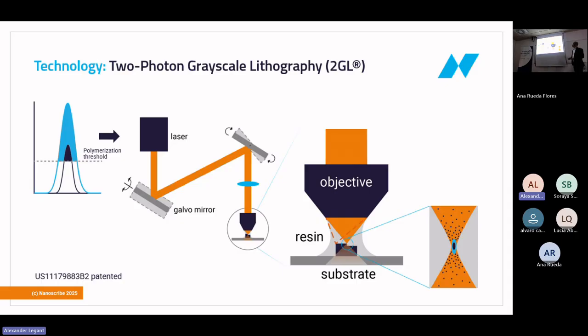Now the next step forward is that we also use two-photon grayscale lithography. We have a patent on that. If you look at what happens at the laser intensity level, at the voxel level, polymerization takes place only if the laser intensity exceeds a certain polymerization threshold. And this area here in bright blue, for example, corresponds to a polymerized area shown on the right side. The volume that is exposed is called volume pixel, or voxel for short.